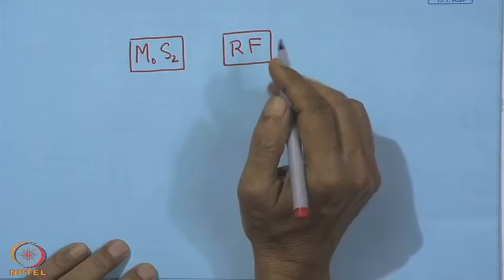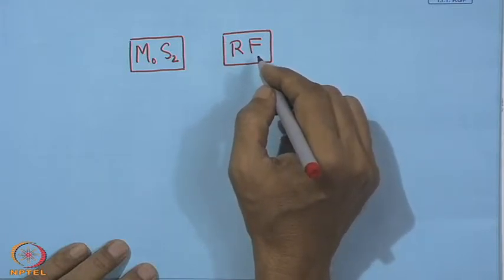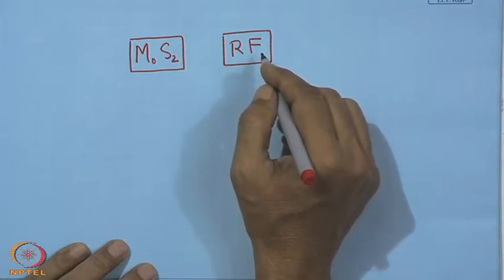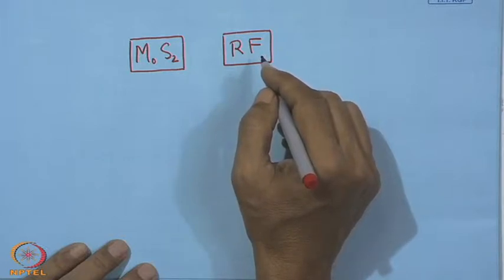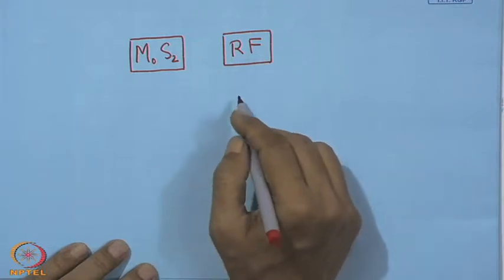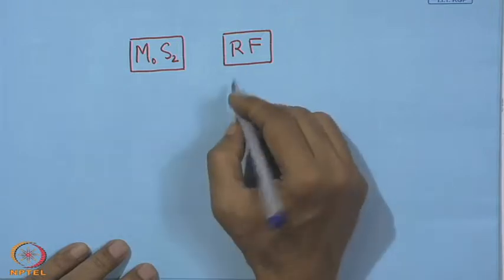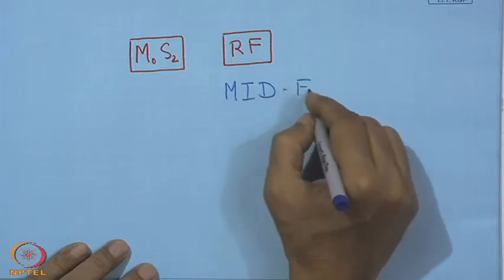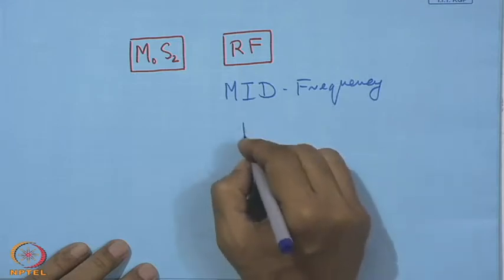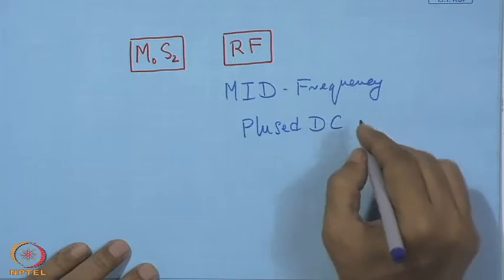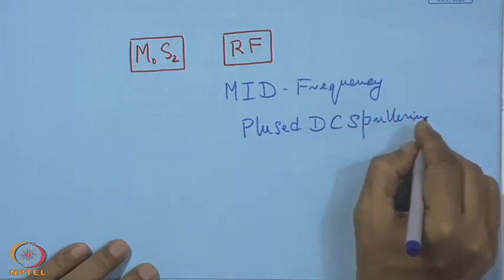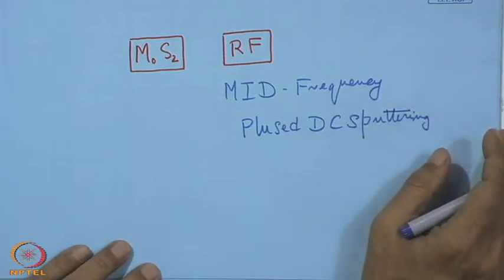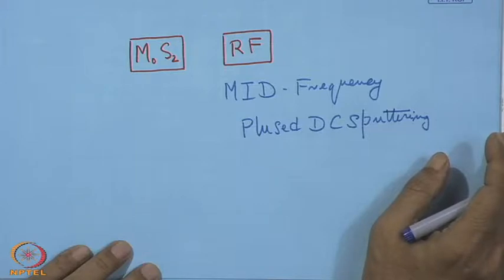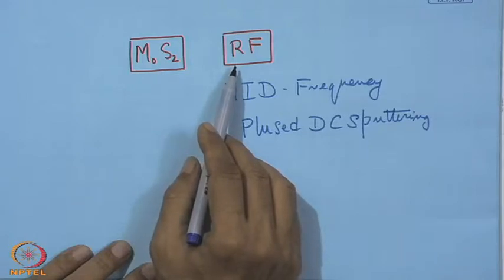But RF has a complexity that is also noted: the complexity of matching the capacitance with an external capacitor, and also the impedance matching. So, that is why later on came into being what we know as mid frequency pulse DC sputtering. Both are very useful in having a coating of molybdenum disulfide on a substrate, and in this case it is mostly for mechanical applications. It is going to be a steel substrate which can be coated with molybdenum disulfide to have better performance